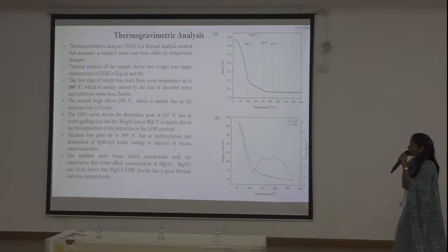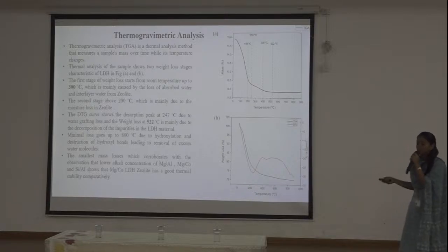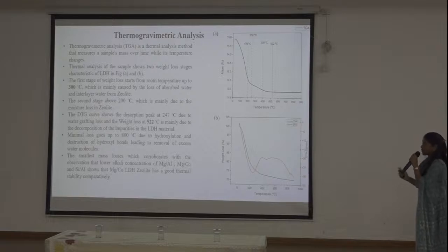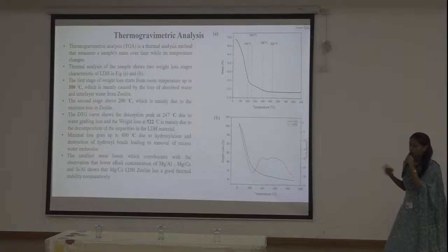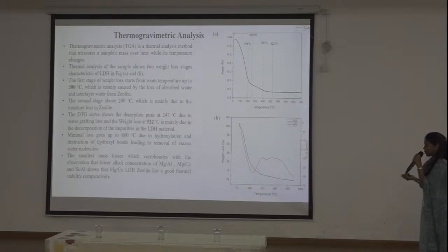Thermogravimetric analysis is a thermal method used to calculate weight loss of the sample with respect to temperature. For this material, we noticed two weight loss stages, found around 300 and 200 degrees, due to absorbed water in the zeolite, and the DTG curve peaks at 247 and 522 degrees are mainly due to impurities in the LDH material.